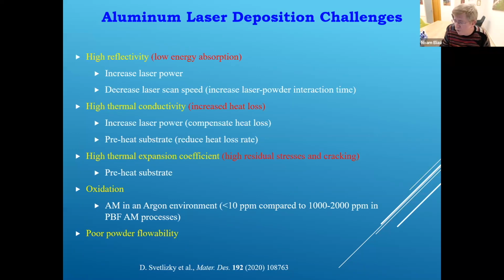So microcity is important. When you look at printing aluminum alloys, it was mentioned in one of the early slides that it's challenging in general in these technologies. Aluminum has high laser reflectivity. This means low energy absorption in the powder, so in order to print aluminum, you need to increase the laser power and decrease the laser scan speed. But aluminum, when it is melted, also has high thermal conductivity, high thermal expansion coefficient, oxidation, and poor powder flowability. Therefore, it is very challenging to print high-quality aluminum-based alloys.